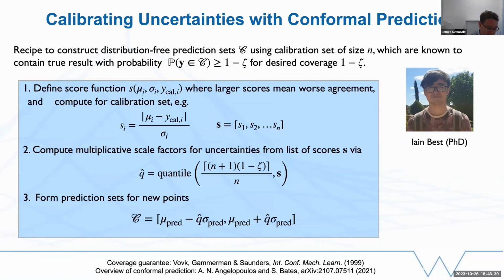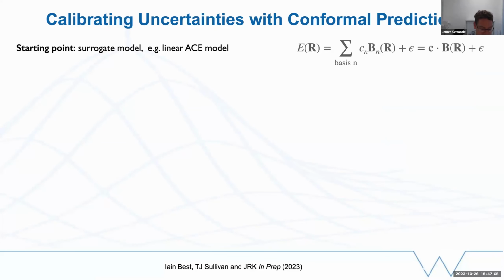And actually you get some formal guarantees that the results that you get will form prediction sets where the true result is guaranteed to lie within the interval given by a lower bound of the mean prediction minus some scaled uncertainty, and an upper bound on the other side. And there's a recipe to decide how much you need to scale the uncertainties in order to make this true. You essentially tune this scale factor on a calibration set, and then you test that it works more widely as well. So how do we apply that to interatomic potentials?